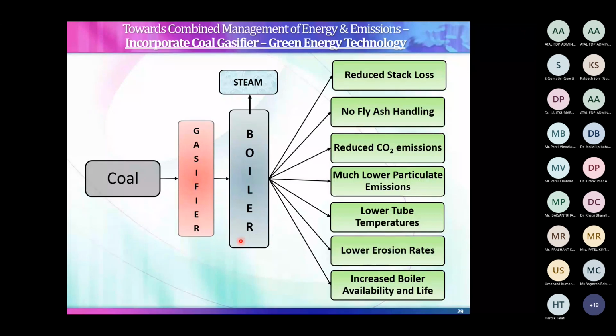So what will happen? There will be a reduction in stack loss. There will not be fly ash present, so no fly ash handling, minimum particulate, reduced CO2, much lower particulate emissions, because there are negligible particles coming, only gas. Lower tube temperatures because the heat transfer surface will be much cleaner. Lower erosion rate because no particles, and because of that increased boiler reliability and life. So the only thing we need to do is design a gasifier and incorporate it here. So I will take you to some gasifier concepts.